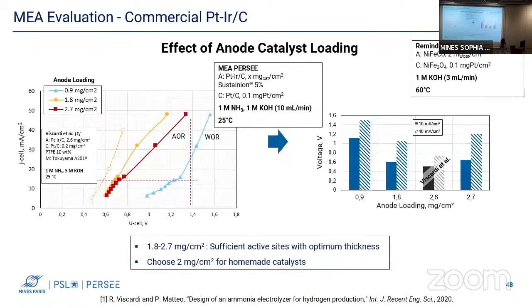As for the anode loading, it was changed from 0.9 to 2.7 milligram per centimeter square. The best conditions were obtained at a loading of 1.8 milligram per centimeter square, and the optimum could be ranging between 1.8 and 2.7, which is conforming to the data reported in the literature. The reason behind that could be the presence of a sufficient number of active sites, but also the optimum thickness of the catalyst layer, which would result in the lowest mass transport limitations and the lowest electrical resistance.